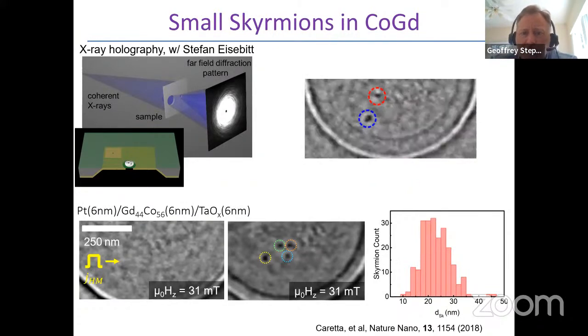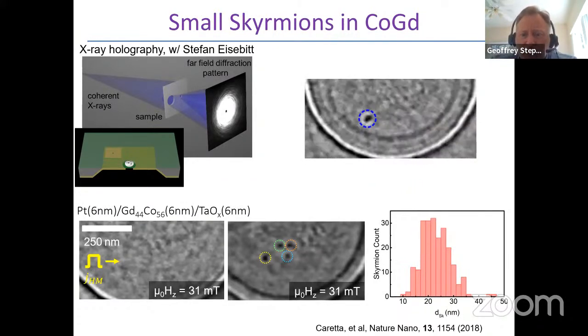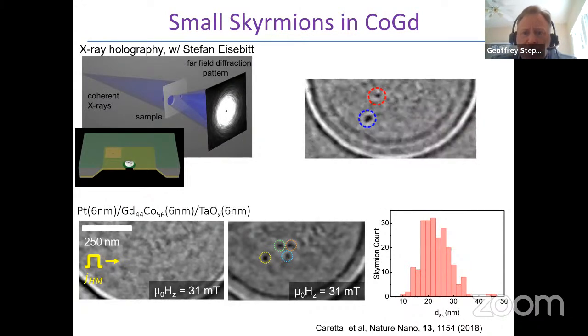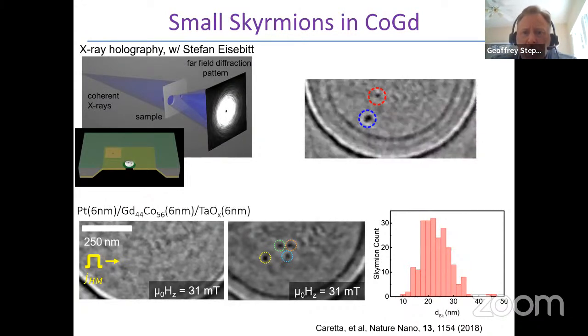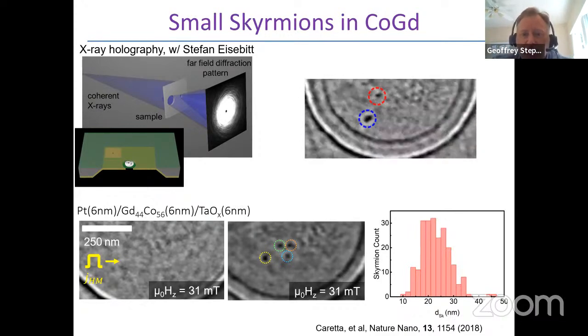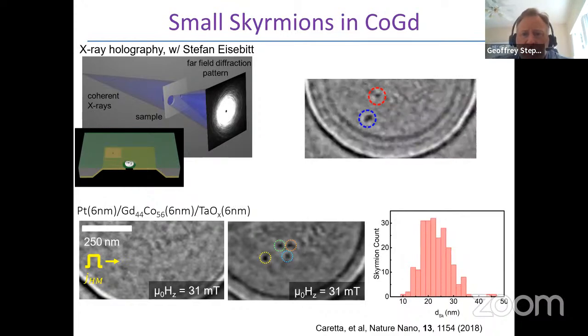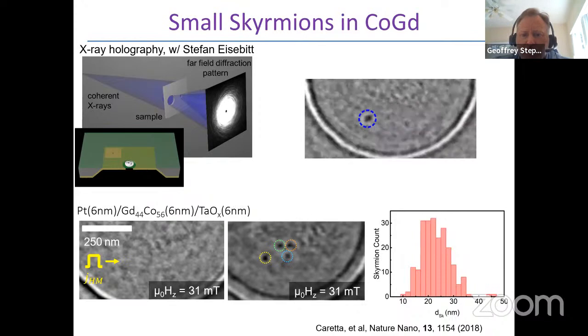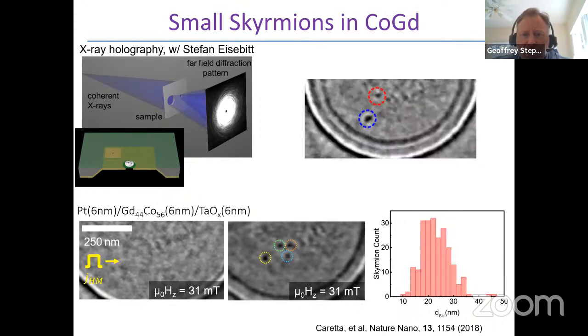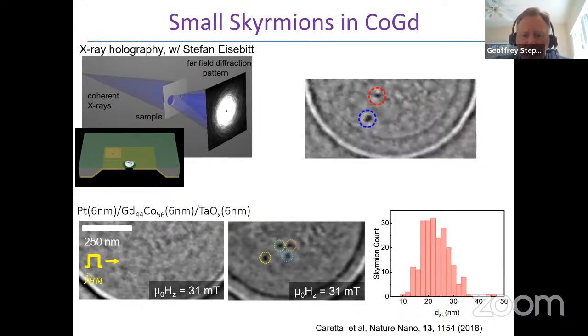But one can also see, by virtue of the size distribution, that the stability isn't infinitely long. So after nucleating several of these skyrmions and just watching them over time, one can see manifestations of the volume energy that keeps them stable. The smaller skyrmion that you see circled in red annihilates after something of the order of tens of minutes, whereas the larger skyrmion tends to be more stable and lives for much longer in these materials.